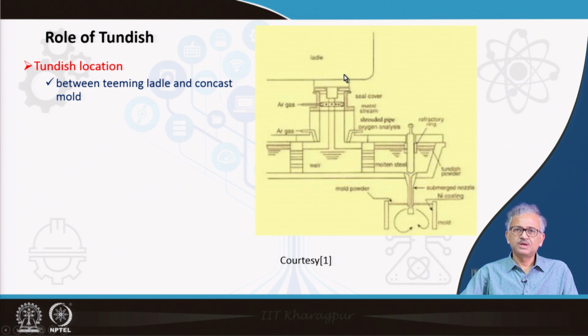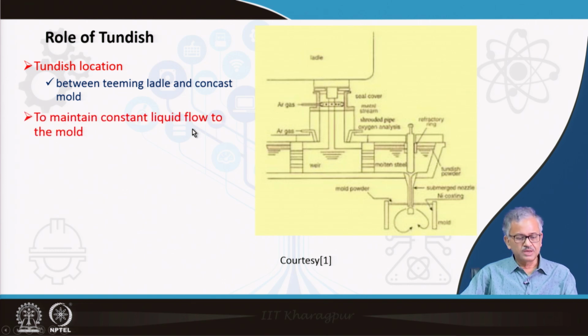Because if you have an open stream, then there is a chance of air oxidation, nitrogen absorption and all these things. So, it is essential, because that will give rise to a lot of inclusions, and during casting a lot of precipitation will come. We do not want that. After the teeming ladle, the tundish is the only inclusion removal station, and after that the steel goes directly into the mold. So, we have to be very cautious such that the liquid stream is not exposed to the atmosphere. Okay. And then this is the tundish. From the tundish, you can control the flow rate to some extent by using what is called the tundish stopper rod. Okay, I will come to that.